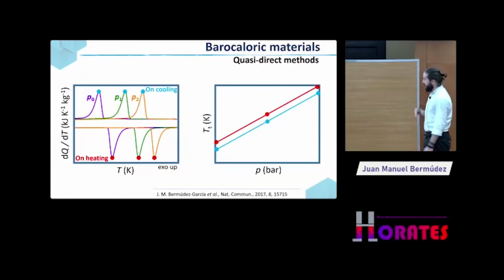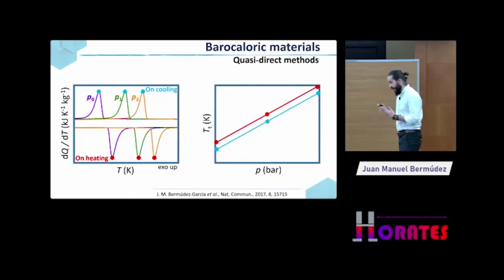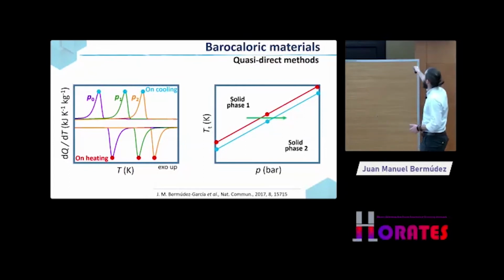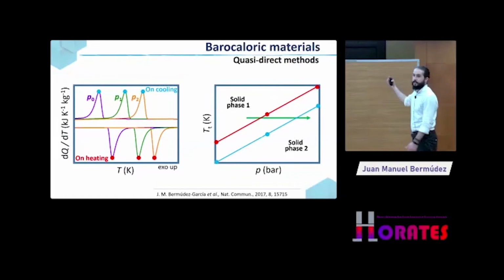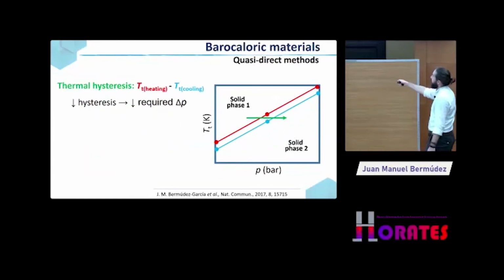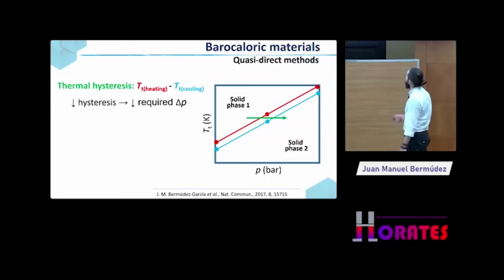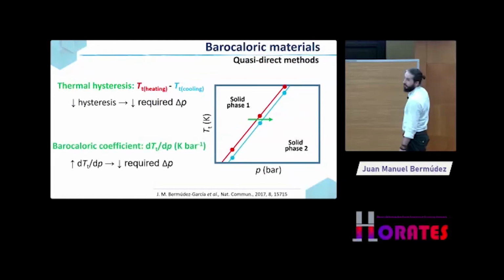And this thermal hysteresis is really important because if you have a low thermal hysteresis, you have to apply a very small pressure to drive the transition from the phase one to the phase two. But if you increase the thermal hysteresis, then this pressure is not enough and you have to increase the pressure. So you are putting more energy into the system, less efficient is going to be your system. And then, so lower hysteresis means less required pressure, which means that the efficiency is going to increase. And then in terms of the barocaloric coefficient, so the larger is this slope, the smaller is going to be the pressure required to drive the transition. So these two parameters are really important in order to design a material for barocaloric properties.